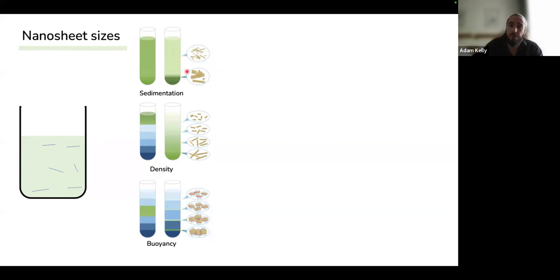Another way of doing this is using a graded density solvent, so a solvent with lots of different densities. And then when you apply centrifugation, the nanosheets will actually sit inside of the layers in between each of the interfaces. And another one then, which is very similar to this, is just by using buoyancy.